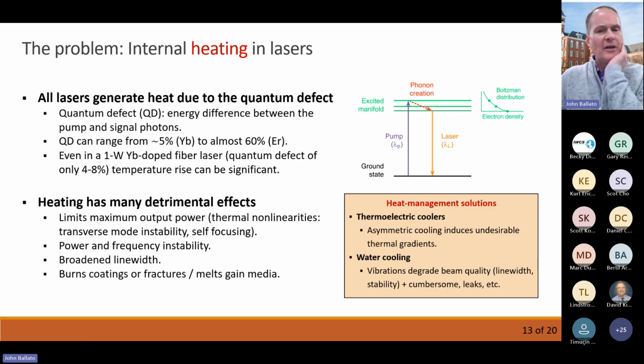And there are a couple of ways of going about doing that, but let's talk quickly about how one does this. So lasers heat because of what's called the quantum defect, right? So there's an energetic penalty. You pump it to a higher energy, there's a relaxation, you get a difference between the pump energy and the emission energy, and that difference goes into heat. That's called the quantum defect. In ytterbium, it's only about 5%. In erbium, it could be as high as 60%. And if you're scaling to hundreds of watts, if not kilowatts, 5% is still a lot.